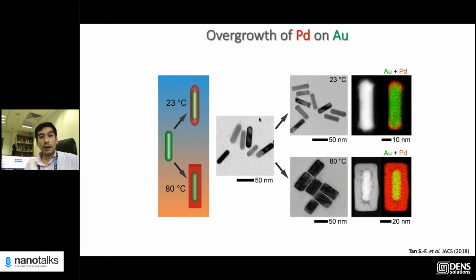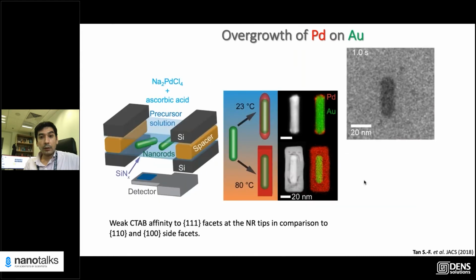So if you start with a nanorod and do your overgrowth reaction of palladium at room temperature, you predominantly deposit palladium on the tips of the nanorod. But if you crank up the reaction temperature, you end up in this kind of coffin type of geometry, where you have a nanoparticle embedded in this cuboidal shape. And in situ liquid cell TEM, for example, allows you to monitor how this process is proceeding.